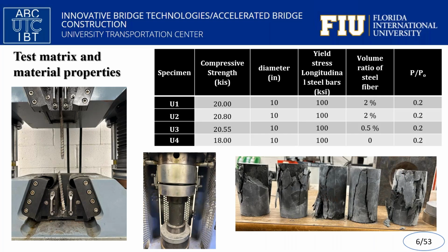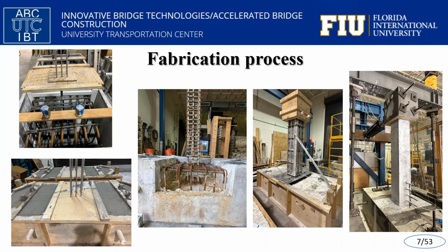To have the material properties, we tested UHPC samples and rebars in our material lab. And these figures show the construction process. First, the reinforcement cage of the foundation was placed inside the footing formwork, and all longitudinal rebars of the column were positioned inside the footing. The outer part of the foundation was then cast with normal strength concrete.